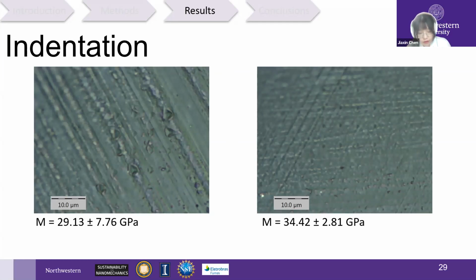Having measured the fracture toughness of alkali-silica gel crystals, we set out to measure the fracture energy, GF, using the Griffith-Irwin formula. First of all, we need to get the elastic modulus. There's a relationship between elastic modulus and indentation modulus. There are two microscopic images of the specimen 1 on the left-hand side and specimen 2 on the right-hand side. It is a really small indent. If we take a closer look, we can see the small triangular points on the surfaces.